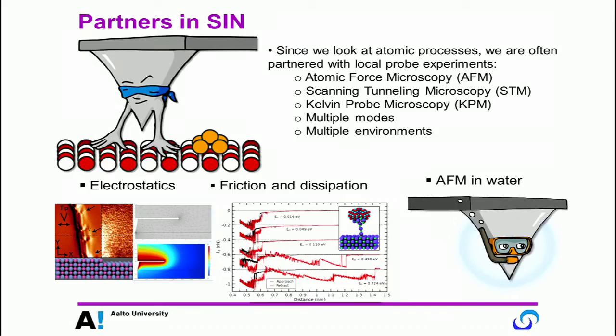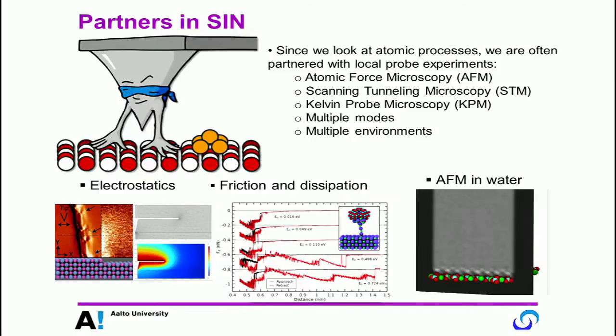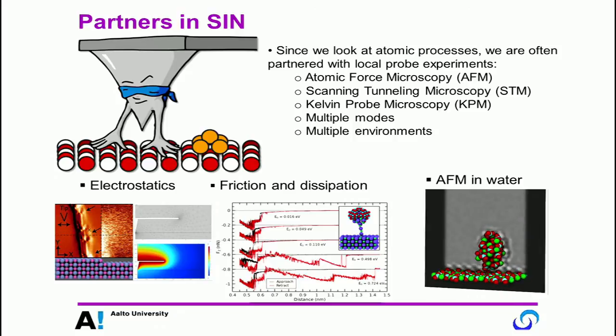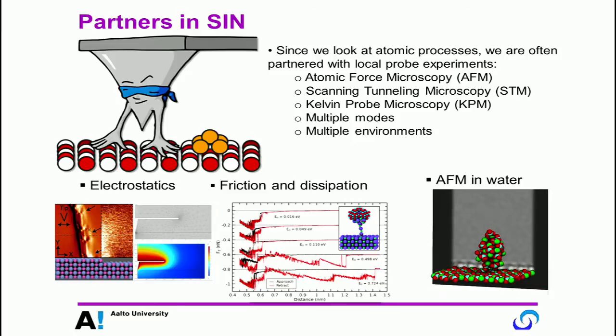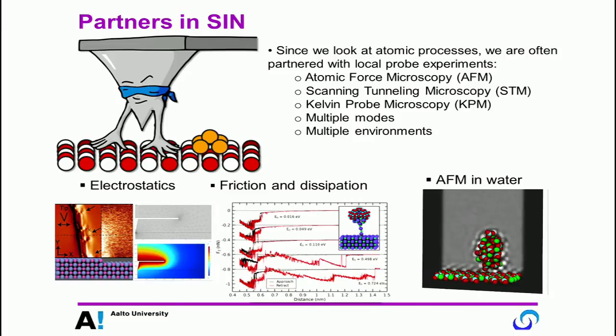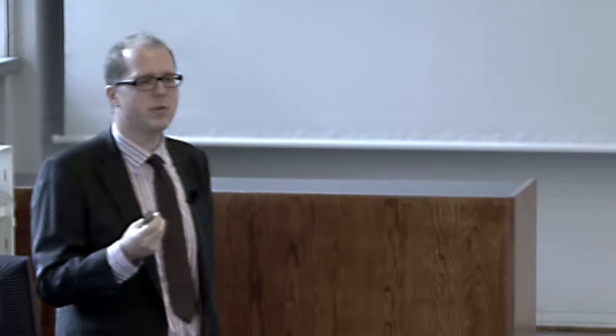And last of all, as we move towards biology and chemistry in liquids, we've also got interested in force microscopy in water, which is really the same thing, measuring the force over atoms and molecules in surfaces, but having a liquid environment, which causes a lot of problems for simulation specialists. And we were able to show here in the contact between a nanoparticle and a surface. And this is calcite, which you're going to hear a little bit about next because it's a very important biomineral. And we were able to show in this grey exactly the density of the water molecule. So this is the average density of the water molecules. And we can show that this completely determines the energy and forces within that system.